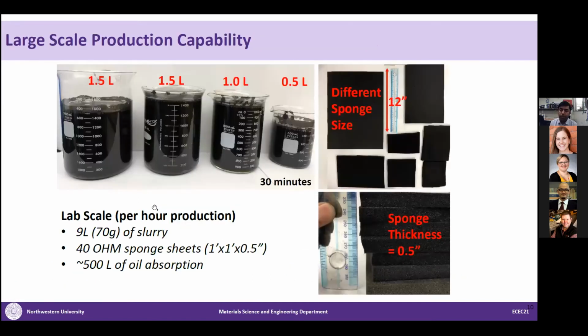The method is very economic and also scalable, because we can produce this nanocomposite slurry in a flow reactor with a high flow rate. What you are seeing here is the production which we have done for 4.5 liters in 30 minutes. So we can generate almost 9 liters per hour of the slurry of this material. And just to give a context, that can coat around 40 OHM sponge sheets, each 1 foot by 1 foot by half-inch thickness. And basically, those sheets are enough to absorb almost 500 liters of oil. So that gives you some context that this method is very scalable.